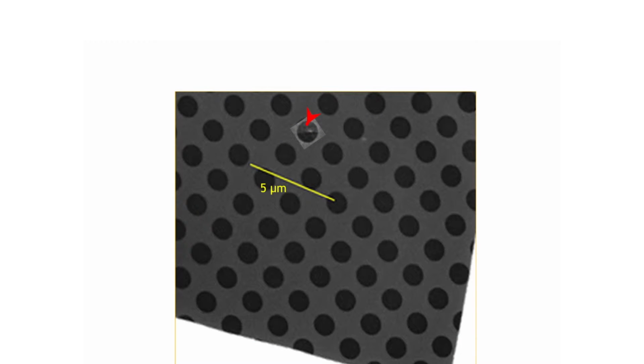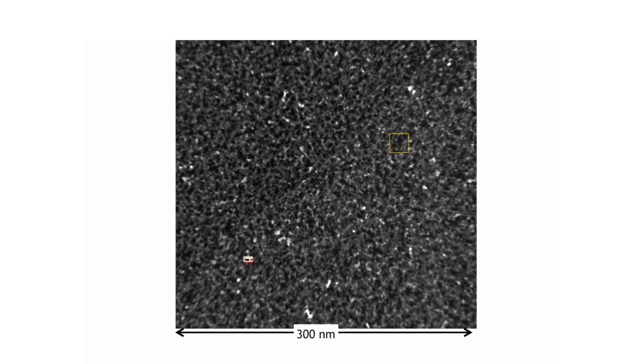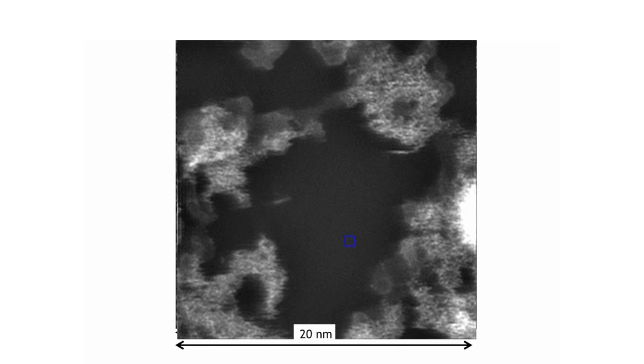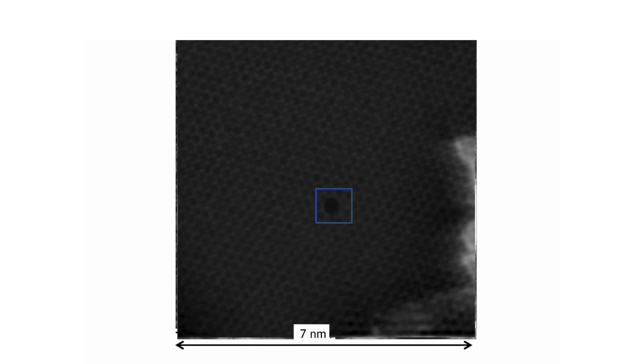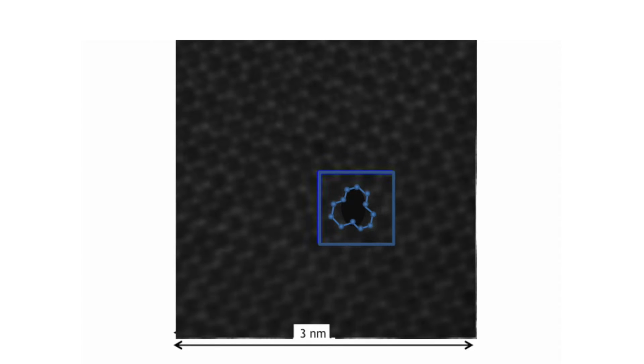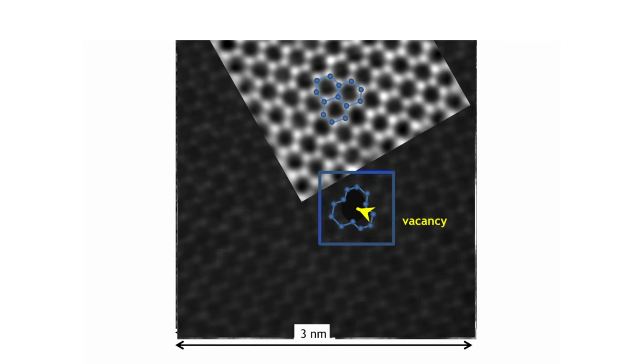If you enlarge it further, that image just shows a lot of crud. So the graphene is actually dirty in itself. So this conception that graphene is clean and wonderful is not true. So what we see here, if we zoom in, we see a clean bit, and if we zoom in further, we can actually see the atomic structure, and we can see the hexagonal lattice, and there is an atom missing, it's a vacancy. And if I enhance the contrast in the perfect surrounding part of the lattice, we can see the perfect hexagonal rings that the ball and stick model is overlaid. We zoom out again, so all the white and grey regions are dirt.